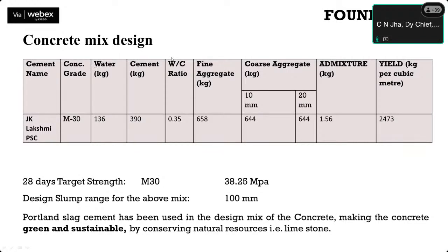This is the concrete mix design. You can see for M30, which is the main component, all the walling, foundation and all, the cement used is slag cement with 390 kg, and the water cement ratio is also very good, that is 0.35, ensuring high strength and durability. If the water cement ratio is lower, then the coarse aggregate and all. And since this is slag cement, about 64% slag component has been used here, so that the proportion of OPC has been conserved.